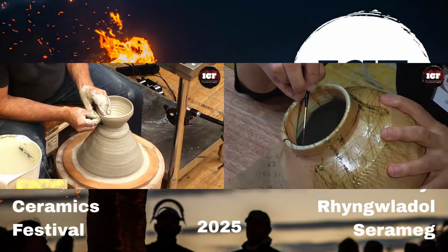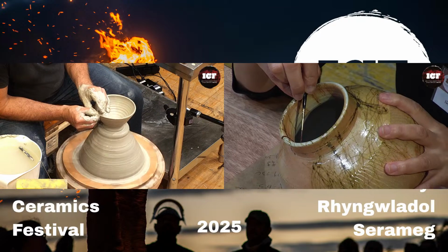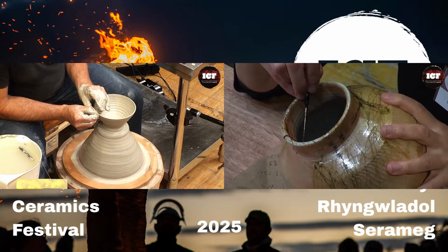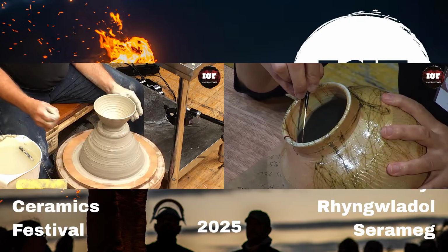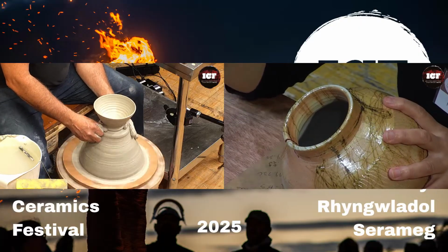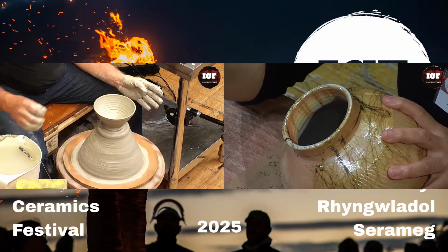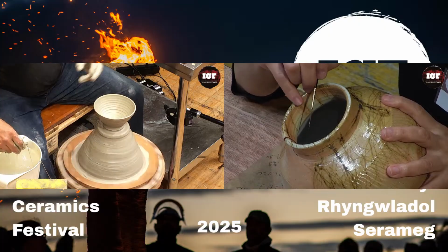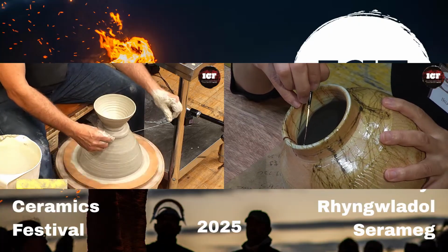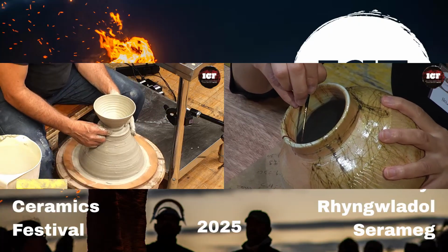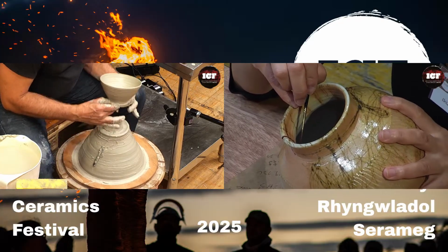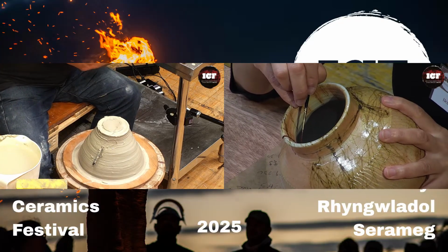So the pink and the gold colour isn't coming from iron at all. It's coming from the interaction of sodium, potassium, and a low silica, high alumina clay. It's the same reaction that gives the pink blush on Shino glazes.